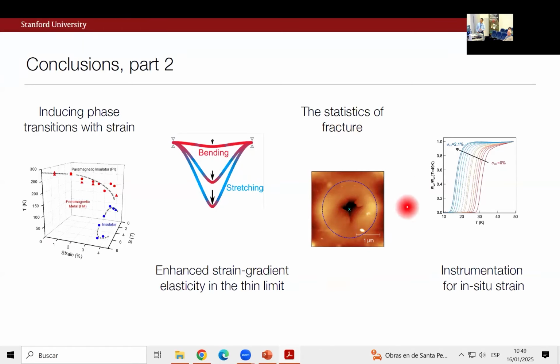I told you a little bit about the statistics of fracture and the opportunities that we have in these sorts of experiments. And finally, I tried to show you a little bit about work we're doing right now to make that very painful experiment a little bit easier, right? Because fracture, temperature matters. Even if you look at these single crystal reports from strontium ruthenate or YBCO, they often report, which is natural according to the story, that by going down to low temperature and applying strain, you can enhance that critical strain by a factor of 5 or 6. And so that again should extend the window we have to explore these parameters.